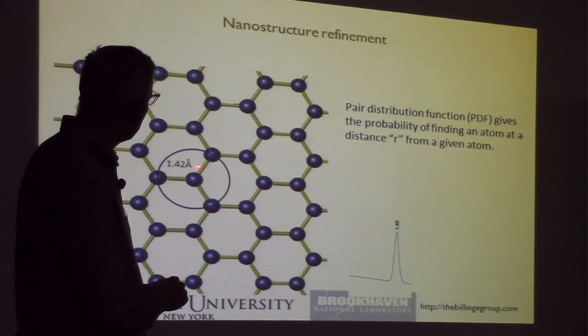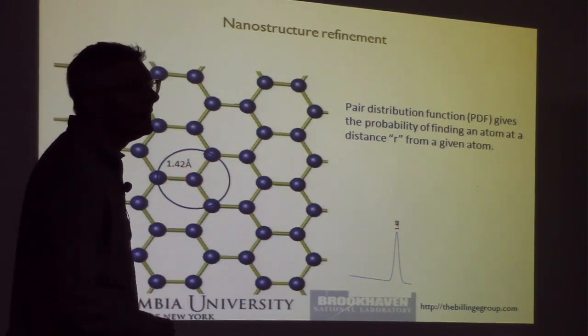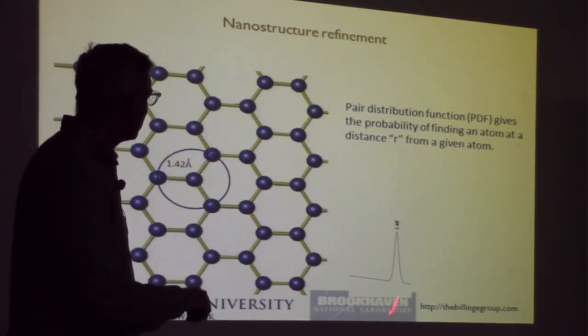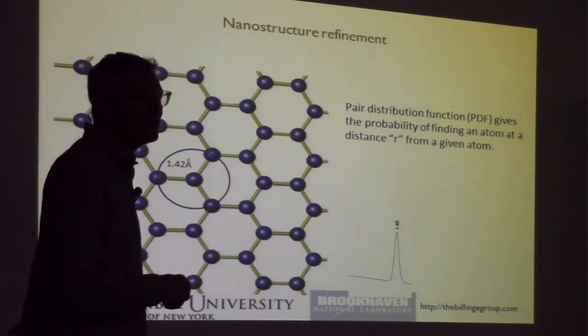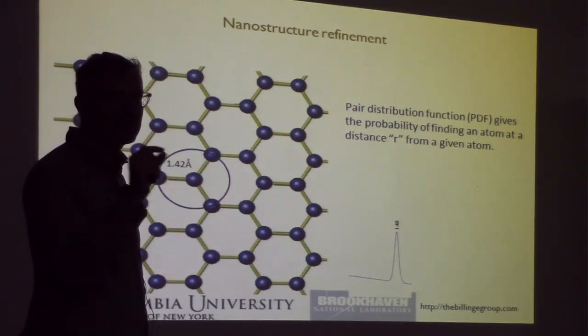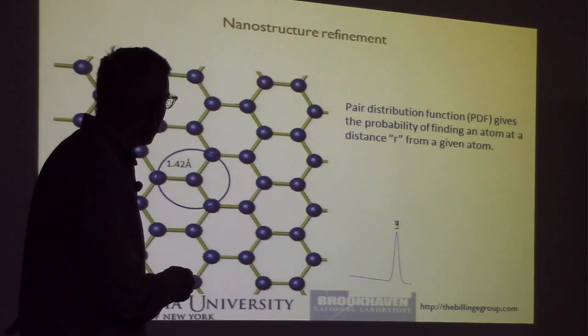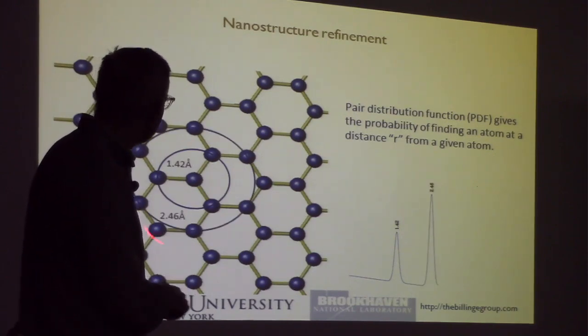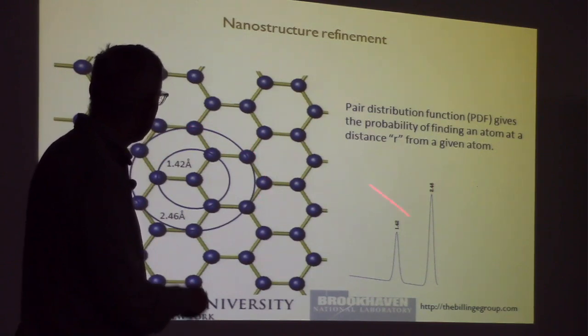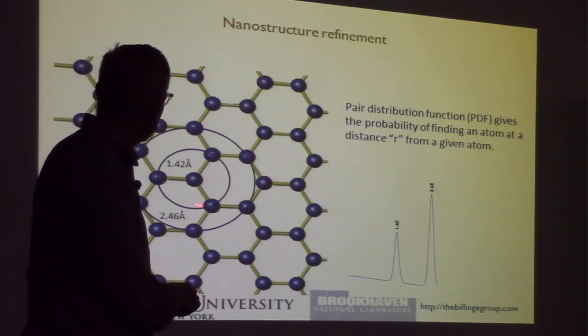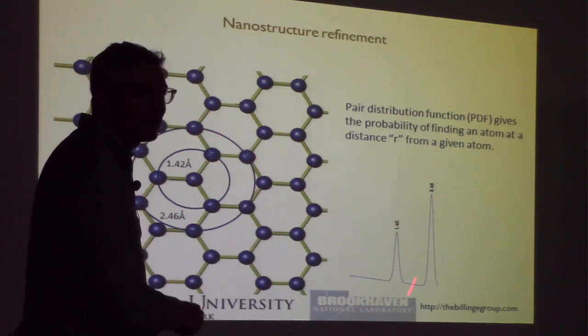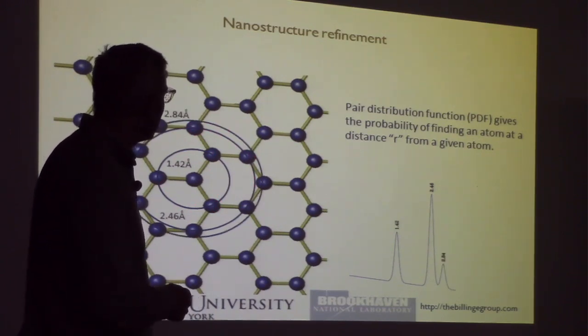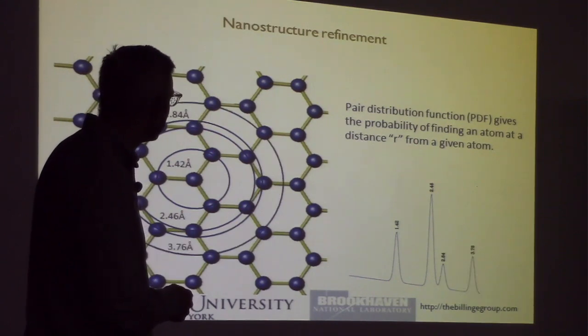So you go out 1.4 angstroms, and you put a peak there. And then you put a delta function there, but you broaden it to make it a Gaussian because of thermal motion, so the atoms are moving. And then you go out further until you find another atom, and you put a peak at that distance. Now this one is a higher peak because it has a higher multiplicity. This was multiplicity 3. This is multiplicity 6. So that peak's higher. And then we go further out, and we find more and more atoms.